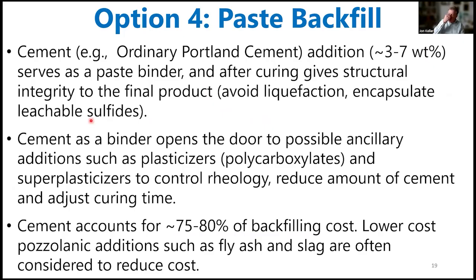One of the nice things, if it's sulfide mill tailings, is that you've encapsulated the sulfides in this paste and it cures, and the sulfides are essentially completely encapsulated and controlled. So the cement as a binder opens up the need to add plasticizers to help control the rheology. So this paste can be pumped from the surface down underground. The big cost is the amount of cement in this operation, so much so that it's been estimated cement accounts for 75 to 80% of the backfilling cost.